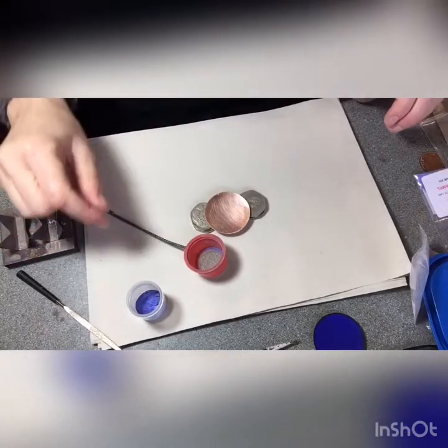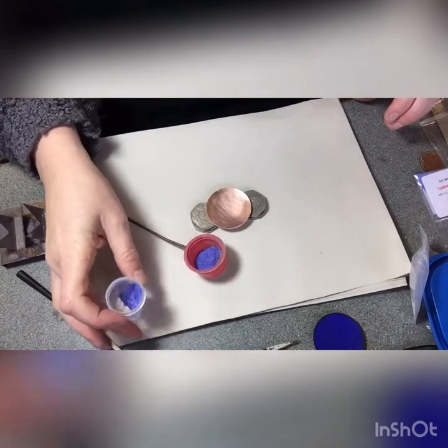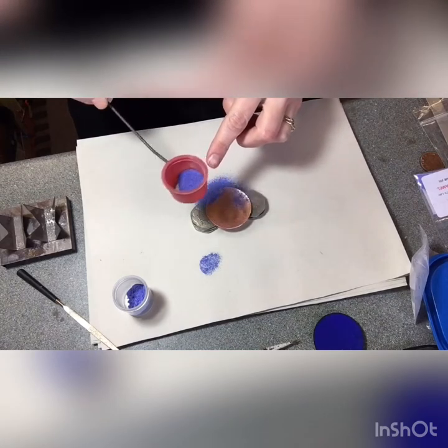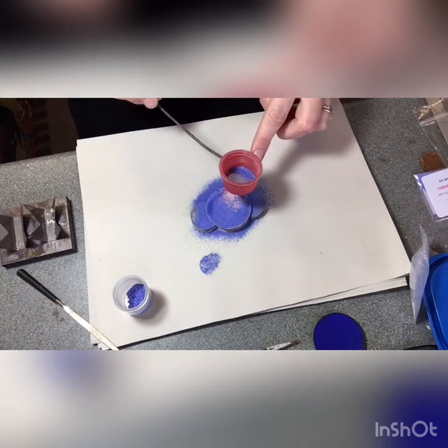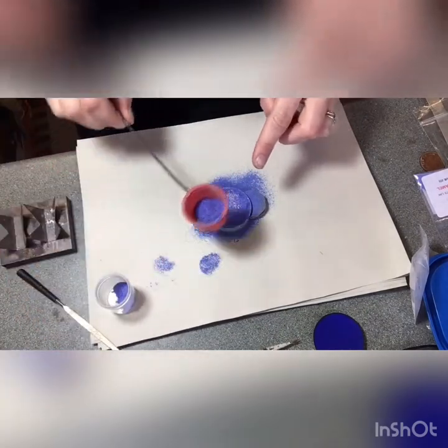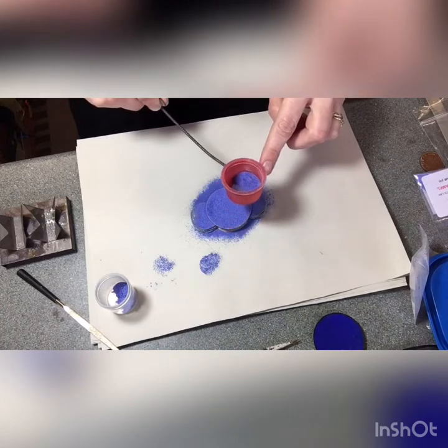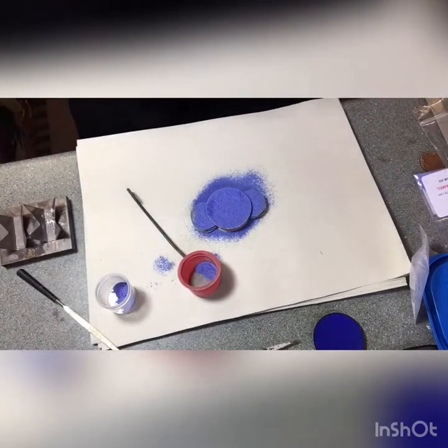The next stage is to apply the glass powder to the copper blank, so I need to tip the powder into my sieve. I'm just going to go around the edge of my pre-cleaned copper blank with the enamel powder, which is ground down glass. When I've covered all the edges I will then go over the central area and just make sure that I can't see any copper. It's better to have two thin layers than one thick one, so if it's getting a little bit thick I might take the powder off and reapply it.